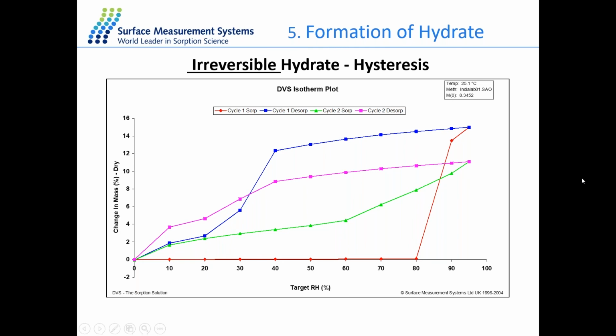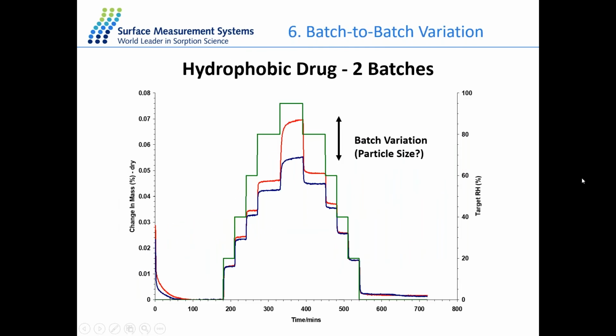So I think the last application I'd like to show here is about the batch-to-batch variation. The DVS balance is quite a sensitive balance with a resolution of 0.1 microgram, and we can detect really small surface sorption differences from the mass uptake. Here, the uptake of the sample is only about 0.07% or less than 0.1%, and there are still some differences between the samples. This difference could be related to the batch-to-batch variation between different samples. And that's the hydrophobic drug.